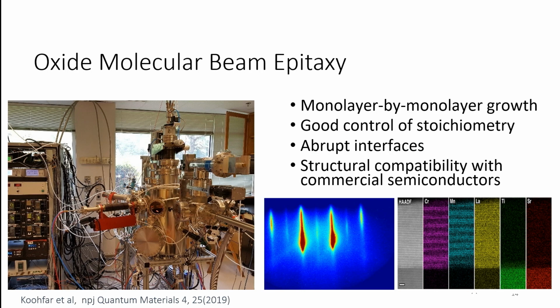All right, so in my lab, we have an MBE system here, and it's an ultra-high vacuum system. So we pump it out. The base pressure in it is in the 10 to the minus 10 torr range. So it's a very clean system. And at the bottom here, we evaporate the high purity metals which constitute the structure we'd like to grow. And so we can control the rate at which we evaporate the materials and grow films. And we typically grow these films at 1 atomic layer per minute. So it's a very, very slow technique.